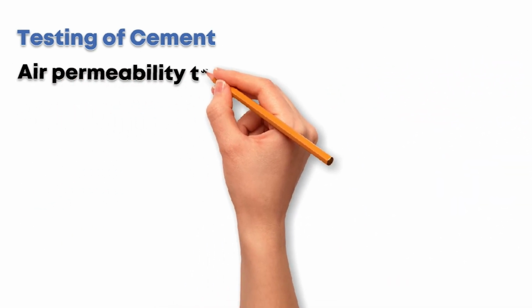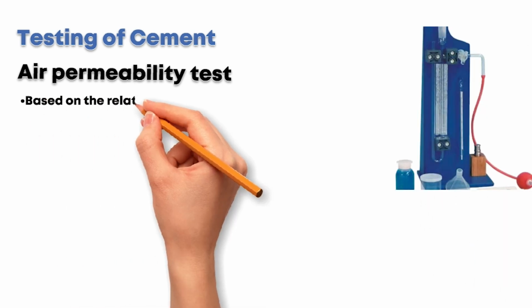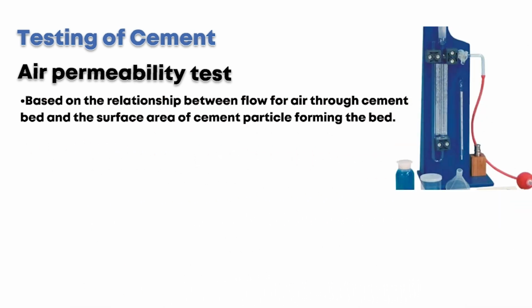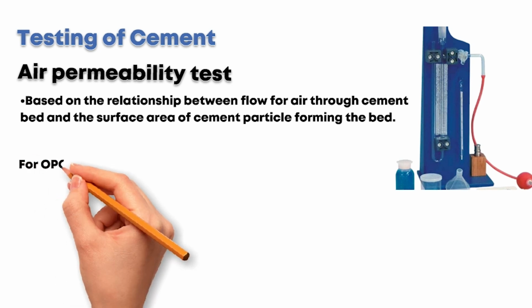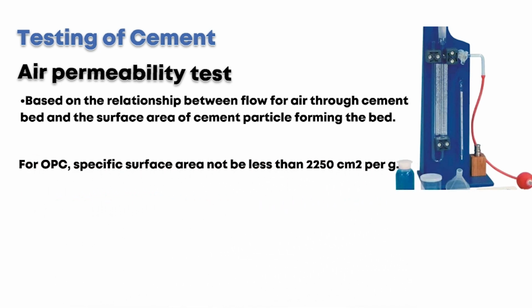cement. The second laboratory test is the air permeability test. Blaine's air permeability apparatus is used, based on the relationship between flow of air through the cement bed and the surface area of cement particles forming the bed. For ordinary Portland cement, the specific surface area should not be less than 2250 square centimeters per gram.